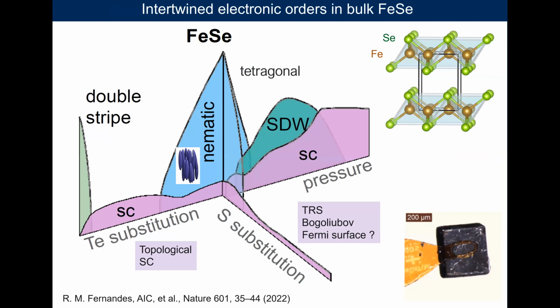So here is a three-dimensional phase diagram of the family of iron selenium. Iron selenium is supposed to be one of the simplest binary material systems. So if we understand a simple system, hopefully we can move forward in understanding complex unconventional superconductivity. And this material is special for many reasons. In the bulk form, these are single crystals grown with chemical vapor transport. It has a nematic electronic phase, which is quite unique in the fact that often there is a magnetic phase following a nematic phase in iron superconductors, but this nematic phase in iron selenium is robust to very low temperature, just before the superconductivity sets in. So that means we are able to understand these nematic phases better using different tuning parameters.